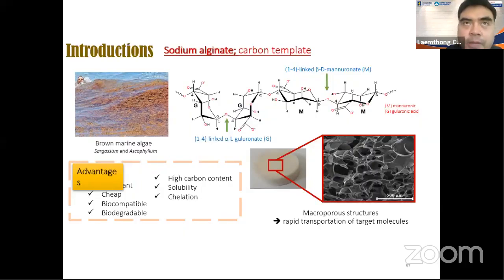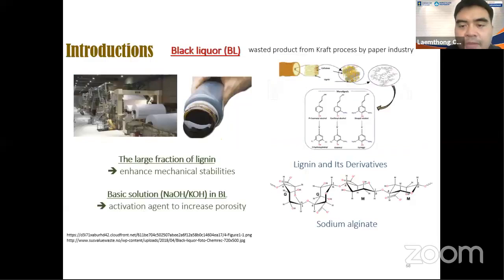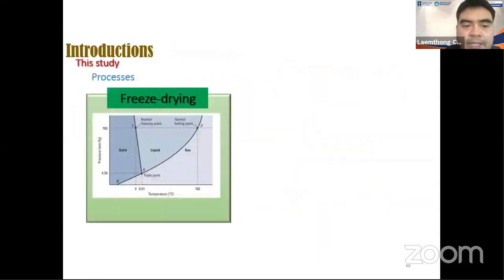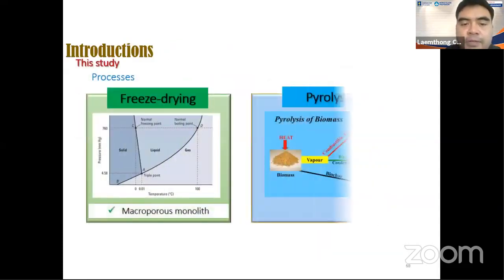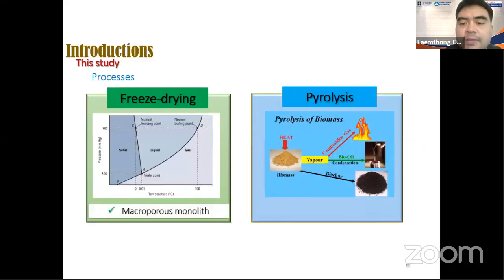But the sodium alginate plays a role as a template in this case, because it can integrate the lignin well into the sodium alginate. Okay, so we mix the things together because there is quite good compatibility between the black liquor and sodium alginate. And then we use the freeze-drying technique, and we do the pyrolysis later.